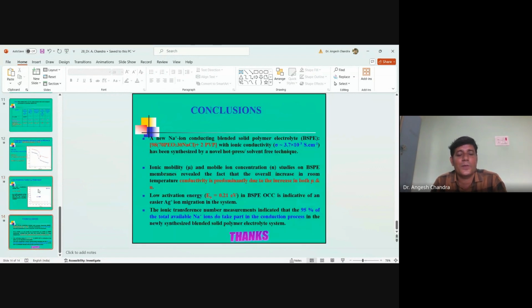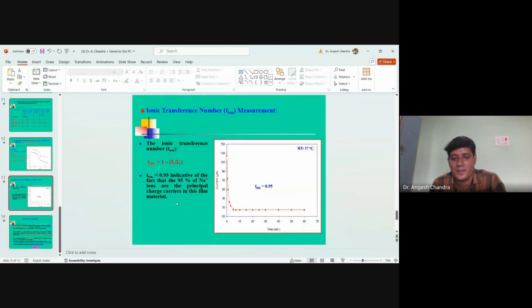Now, this figure shows the ionic transference number measurement. It means how much percentage of ions are mobile in these systems. With the help of this formula, 1 minus I_e upon I_T, and with the help of this graph, we have calculated the ionic transference number, and we have found t_ion is 0.95. It means 95% of sodium ions do take part in the conduction process, and these are responsible for conductivity enhancement in the blended solid polymer electrolytes.